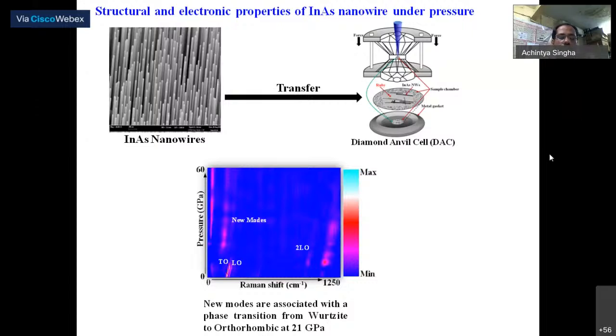As I said before, if you apply pressure, a structural transformation will occur. If you see this color plot, there are initial Raman modes, the LO and TO modes. After some pressure they vanish and new modes appear. These new modes are the signature of a new phase of the system.